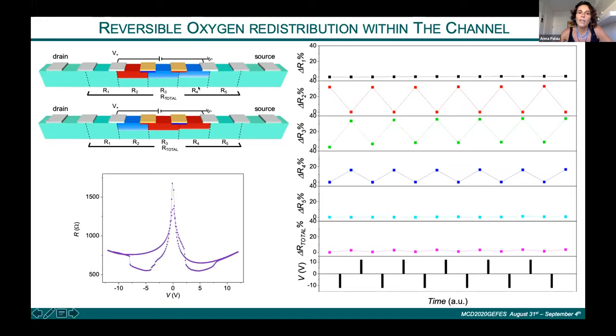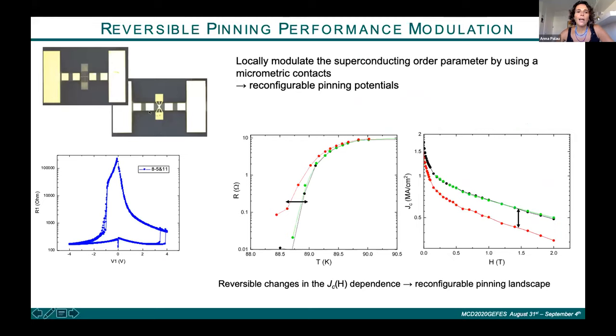For example, here we have tested this distribution of oxygens in a drain source channel with multiple gates. By inducing a polarization between these two gates, we observe that close to the gates we have, for example here, a deoxygenation of the system, and here an oxygenation, because the oxygens reorder inside the bridge. So in these parts of the bridge we have one behavior and the complementary in the other part. And the sum of the two effects is zero because we have conservation of oxygen. And finally, I'll show the experiments that we have started to perform to see if these bridges can be used to change the pinning properties of these systems.